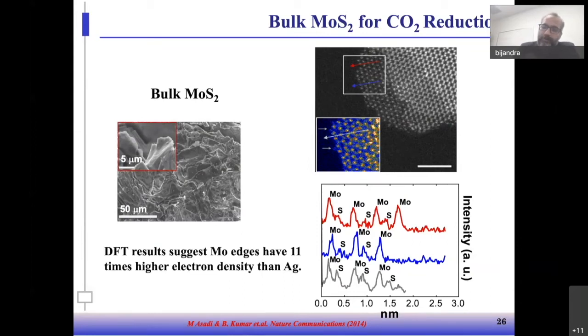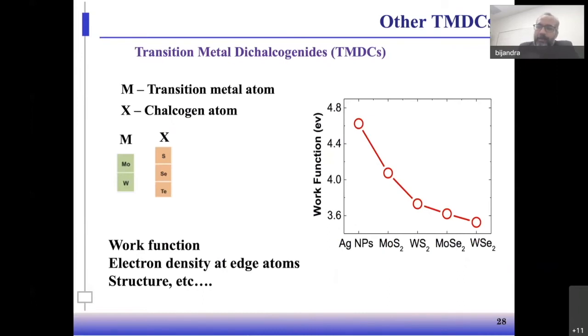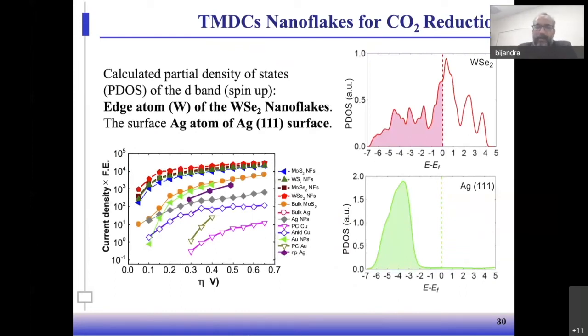CO2 electrochemical reduction reaction. We also tested other types of TMDC catalysts like MoS2, WS2, MoSe2, or WSe2, because they have a higher electrochemical surface area, and additionally they have a low work function. So low work function and higher electron density at the edge atom can provide a better catalyst here. And when we tested MoS2, MoSe2, WS2, WSe2, the different catalysts, the WSe2 catalyst was the best one, with at least 1,000 times higher performance in comparison to noble metal catalyst. The higher performance is attributed to these edge atoms, which have low work function and higher energy density of electron. So that's why they are great catalysts in terms of converting CO2.